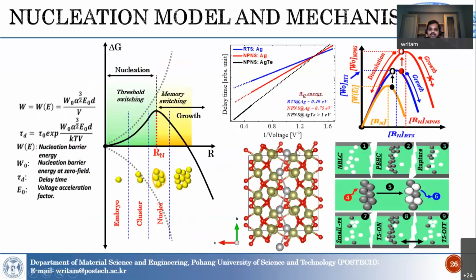To understand these behaviors, consider the simple nucleation behavior. If we consider this as the radius of the filament, after a critical radius, the memory switching behavior can happen, and below the critical radius, the nucleation process is very limited, so full filament growth is not possible. This region is suitable for threshold switching behavior.